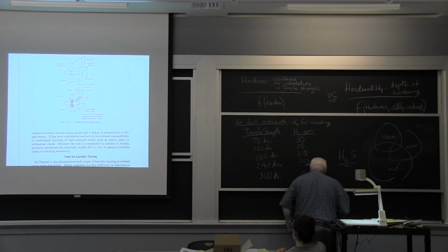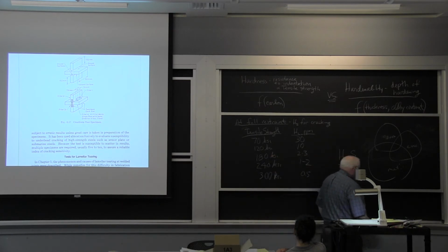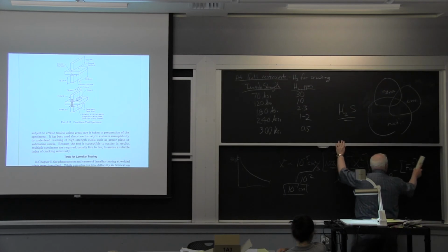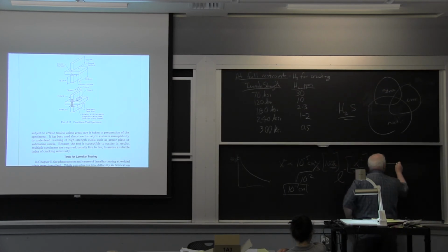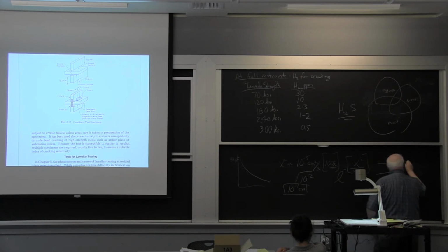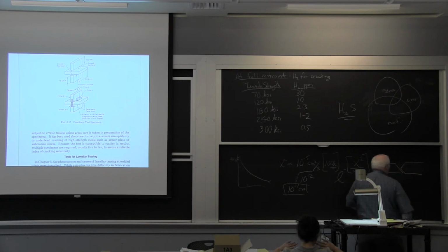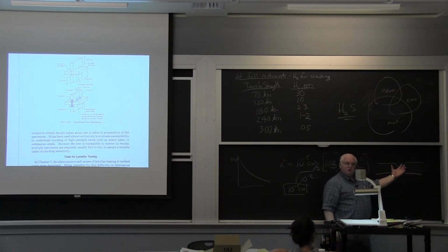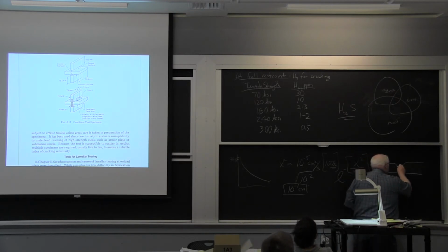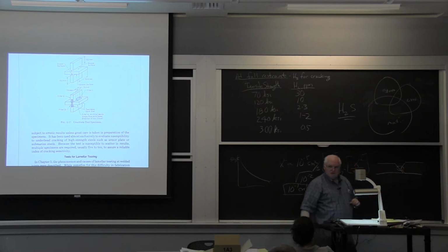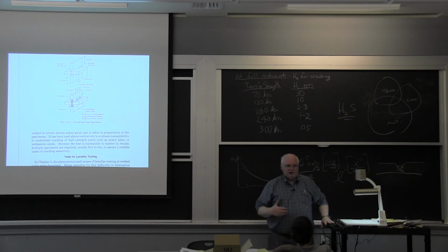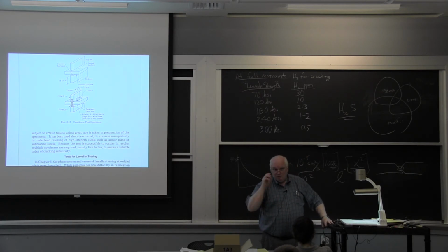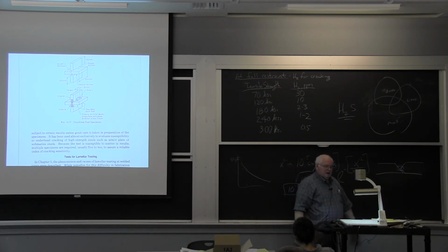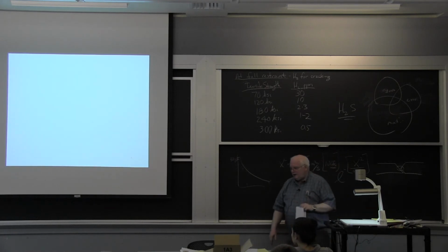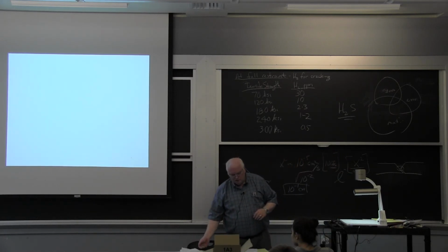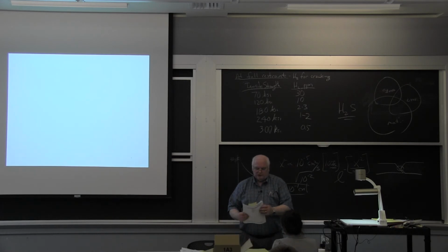The Japanese had one they called the Tekken test, T-E-K-K-E-N. Tekken means railroad in Japan. So guess what industry this came out of? They used to call it the Y-groove test. And the reason they liked it is because it was easy to flame cut. You basically take your 2 plates and make a Y with the joint preparation. And then you put a weld right in here, and they found that was a terrible geometry in terms of residual stresses, and they could get hydrogen cracking. So in Japan, they'll talk about Y-groove tests or Tekken test. That was their test. There are literally dozens of these type of little laboratory tests to try to simulate the restraint that you get in a real welding situation.